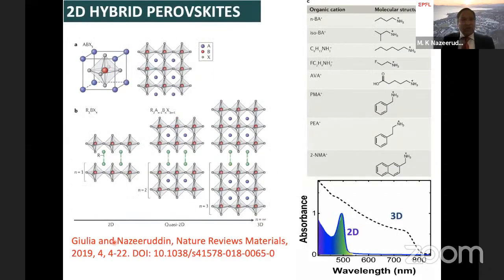So now I come back to the perovskites. Within the perovskites, there is a subclass of materials, that's the low dimensional perovskite, which we will discuss on this slide. So what you see on the left side, this is the perovskite material. Imagine the lead as an octahedral complex. Iodides are corner shared in all these complexes, forming a three-dimensional network. And then the charge compensation is carried out by inserting the cation in the cavity. Let's say this is a three-dimensional perovskite.